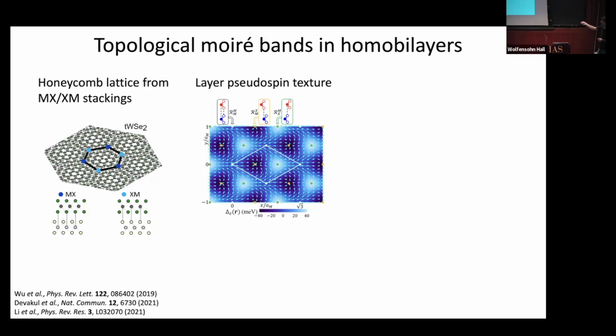In this twisted homobilayer system, the low energy effective Moiré sites form a honeycomb lattice of MX and XM sites. So in the zero displacement field limit, as we heard a couple of days ago, this forms a honeycomb lattice with a skyrmion layer pseudospin texture, and this endows the system with topological bands.